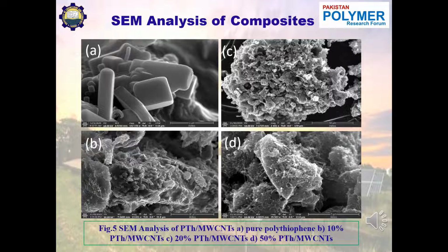The images obtained from SEM analysis show that no individual agglomerates of polythiophene or multi-walled carbon nanotubes are formed, which depicts that multi-walled carbon nanotubes provide the surface for polythiophene for nucleation growth. Moreover, the dispersion of MWCNT improved up to a certain quantity and then decreased.